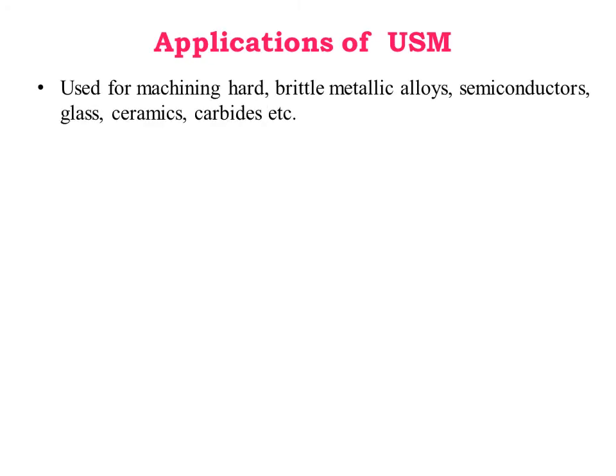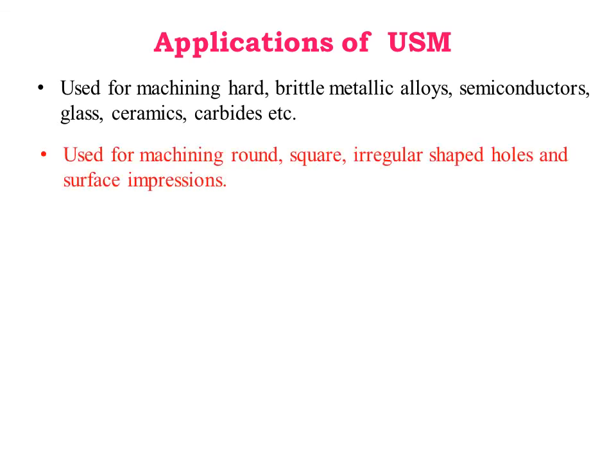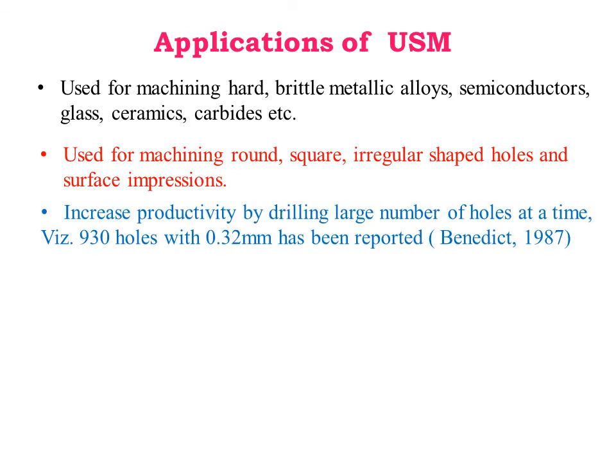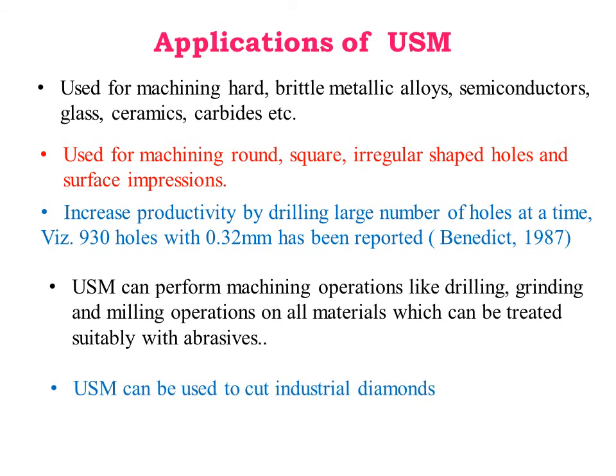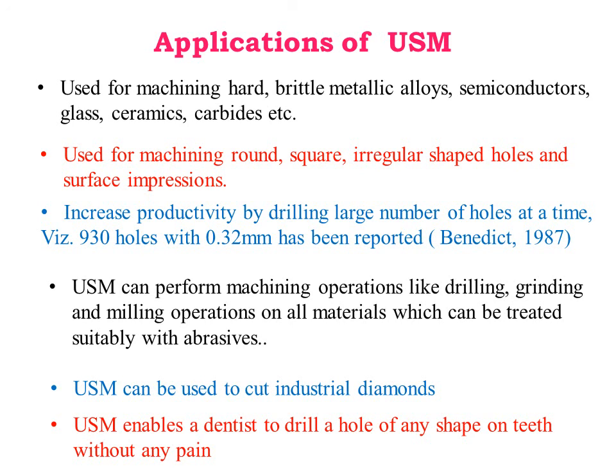Applications of USM: it is used for machining hard and brittle metallic alloys, semiconductors, glass, ceramics, carbides, etc. It can machine round, square, and irregularly shaped holes and surface impressions. Productivity is increased by drilling large numbers of holes simultaneously — 930 holes of 0.32 mm has been reported by Benedict in 1987. USM can perform drilling, grinding, and milling operations on all materials that can be treated suitably with abrasives. It can also be used to cut industrial diamonds, and it enables a dentist to drill a hole of any shape in teeth without pain.